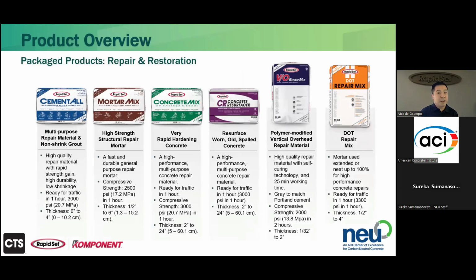So I'm going to switch gears now away from bulk and over to our packaged products. We have over 50 cementitious packaged products, at least that's how many we have on our website. I'm highlighting 6 to demonstrate a variety of use cases and applications. The first 3 on the left, CementAll, mortar mix, and concrete mix, are our bread and butter. They're pretty much keep it simple formulations, designed to be as all-purpose as possible. All of these are going to achieve 2,500 to 3,000 psi in 1 hour, as mixed per the instructions on the bag.